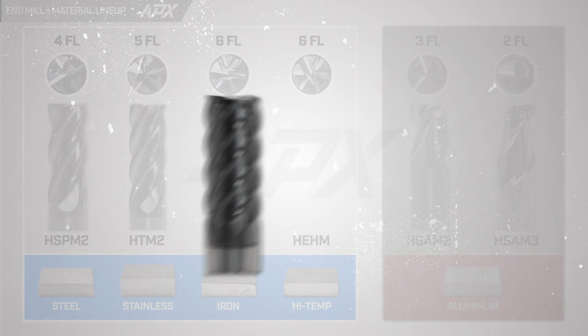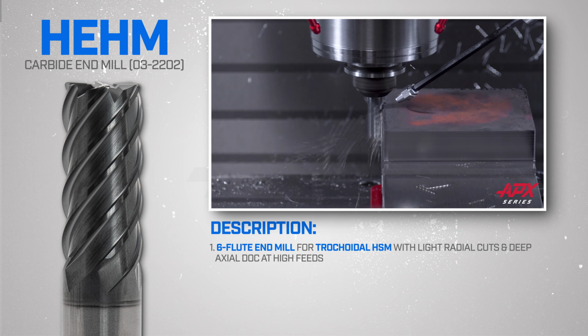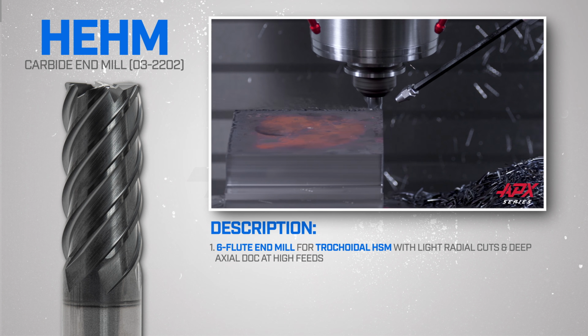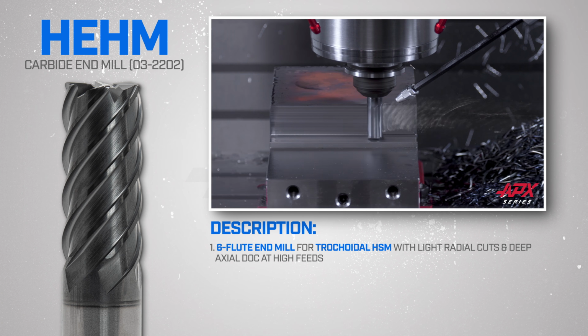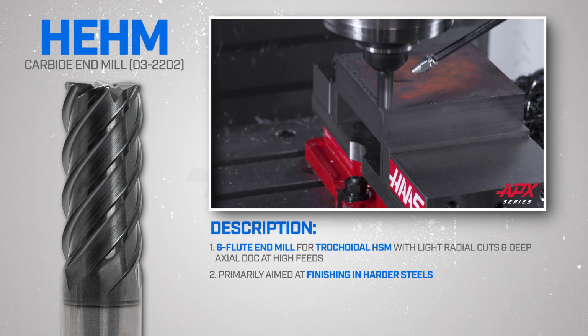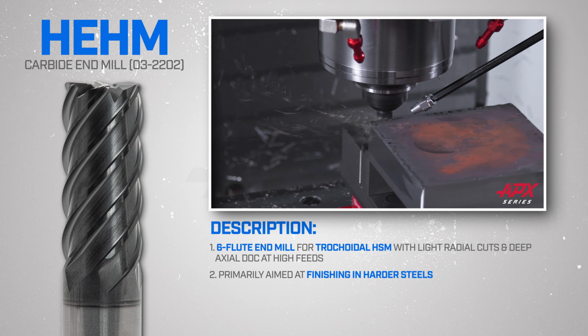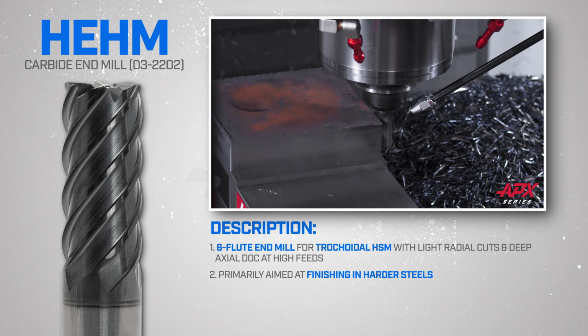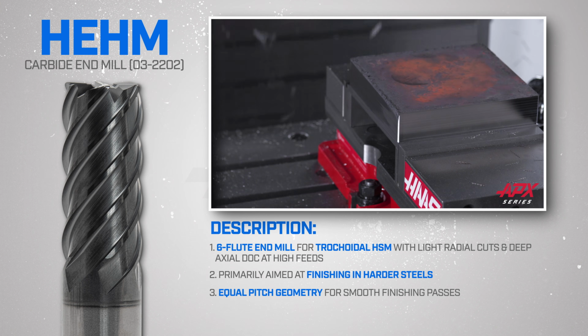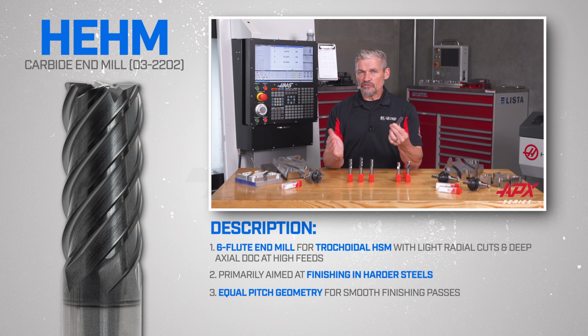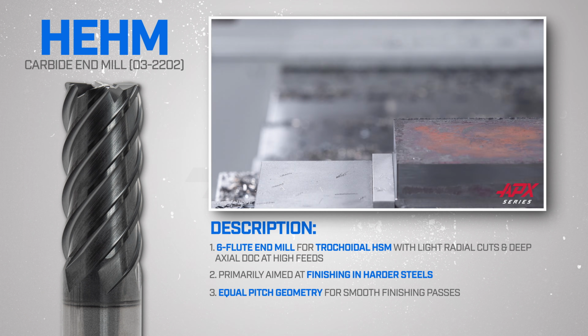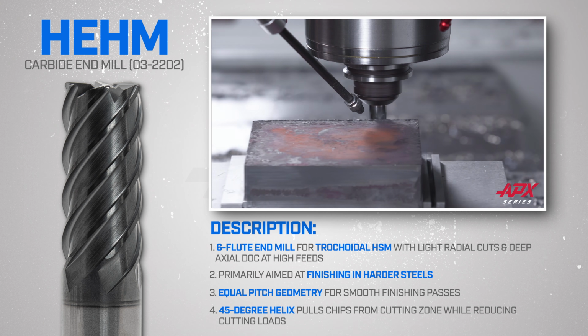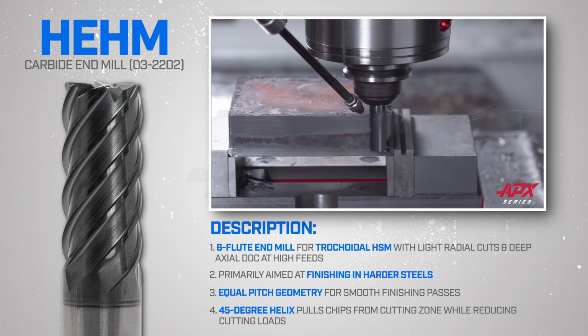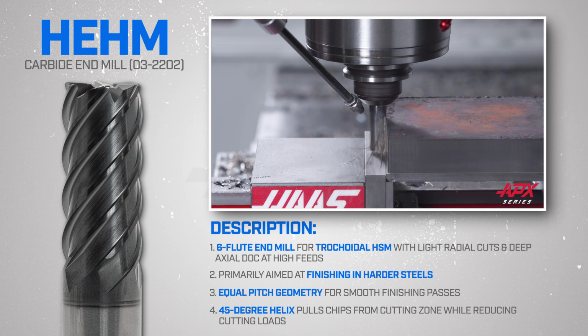The HEHM end mill is also a 6-flute tool, designed for HSM trochoidal tool pass, but this time with lighter radial cuts and deep axial depth of cut at high feed rates. This end mill is primarily aimed at finishing in harder steels where the increased core thickness maximizes stability and resistance to deflection when cutting these harder materials. For finishing operations, the equal pitch geometry on these tools tends to give smooth surface finishes where there isn't as much concern for harmonics and chatter being generated with these lighter cuts. But like the HEPM, this tool pulls chips out of the cutting zone with its 45-degree helix while simultaneously reducing the cutting loads in these harder materials. The HEHM is built for confidence-inspiring finishing in harder steels.